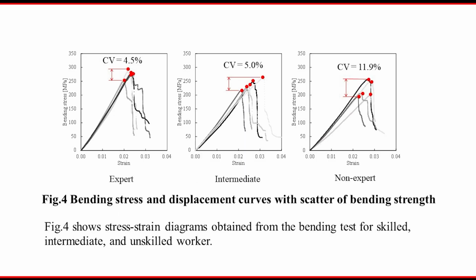This is the result of the bending test. This is the stress-strain curve. Left side is expert, middle is intermediate, right side is non-expert. Here you can see some difference in the stress-strain curves of the bending. In the figures, we show the CV. CV means coefficient of variation of the bending strength data. The coefficient of variation of the strength of the expert is 4.5%, the intermediate person 5%, but the non-expert has a very large 11.9%. So the scatter of the strength is very large in the non-expert.